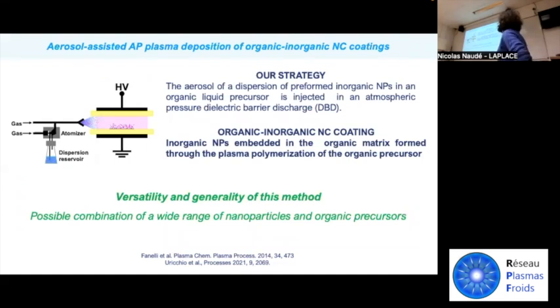Let me briefly describe the strategy we use. In principle, it's a very simple strategy. The DBD is fed by a transport gas and a main gas and the aerosol of a dispersion of preformed inorganic nanoparticles in an organic liquid precursor. This leads to an organic-inorganic nanocomposite layer that consists of inorganic nanoparticles embedded in the organic matrix formed through the plasma polymerization of the solvent of the dispersion. This is one of the possible approaches to obtain organic-inorganic nanocomposite coatings by aerosol-assisted plasma processes. We are using this approach in our work.